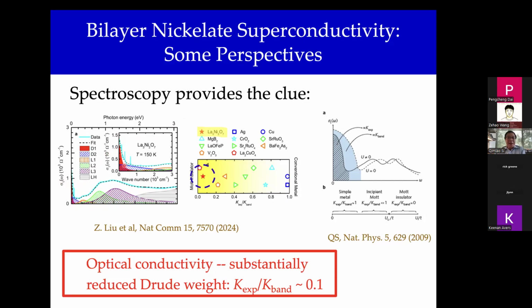Precisely which part should be counted as the Drude part, etc., is a little bit of a complicated issue in these multi-orbital, multi-band systems, but one can get the order of magnitude of the Drude weight. And the measured Drude weight is substantially smaller than the non-interacting Drude weight. And so one could put this ratio, the measured Drude weight over the non-interacting Drude weight, in a chart like this.